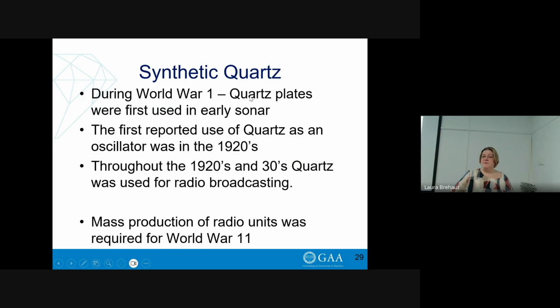The quartz was most valuable during the First World War, and it became one of the most critical areas of scientific exploration to try to manufacture quartz crystals for the sonar and for the radios. They needed to have quartz crystals that were very, very clean and very, very pure. But as well as that, quartz often has twinning in it. So we get Dauphiné twinning and Brazil law twinning. They need to have rock crystal, and it needs to be free of dislocations. So that means irregularities in the crystal structure, and it needs to be free of any twinning, which is very, very difficult to find naturally, the material that was of use for the war effort for these new instruments that were coming online. So they developed a way of manufacturing quartz crystals.